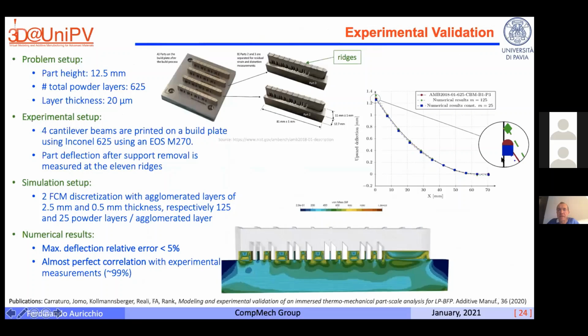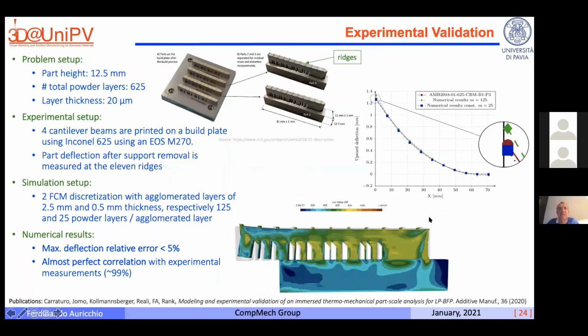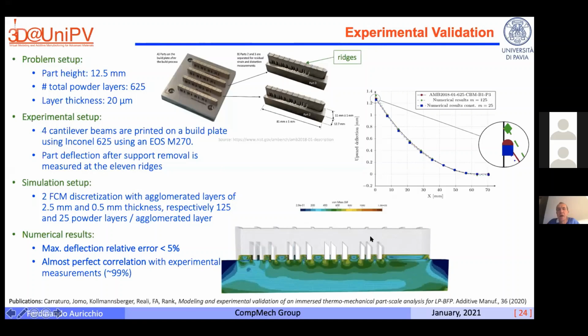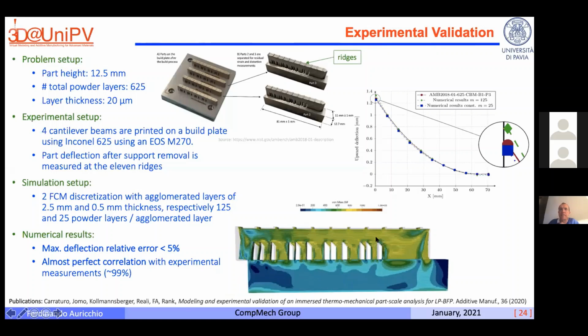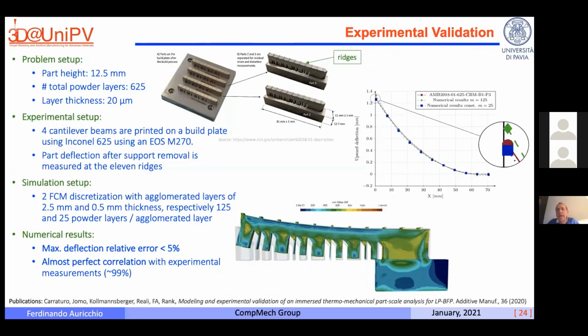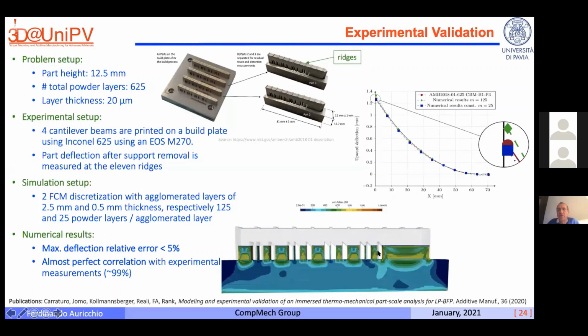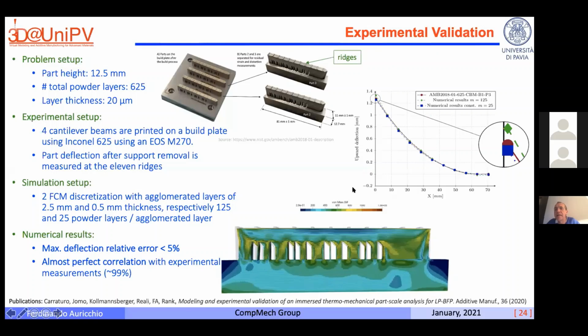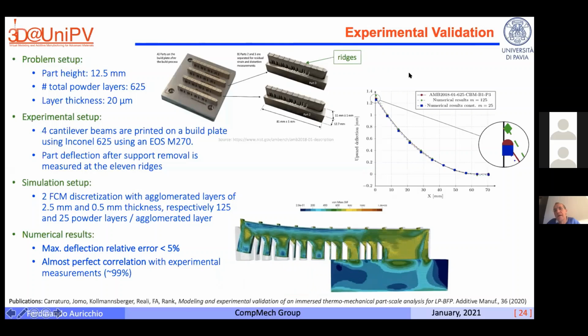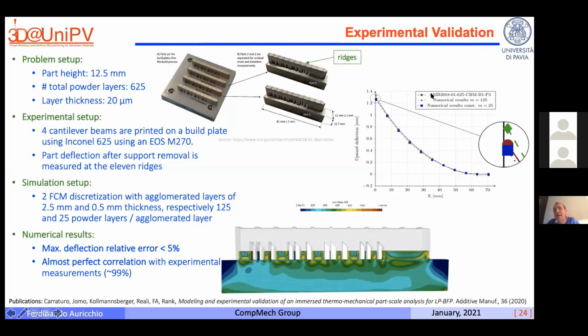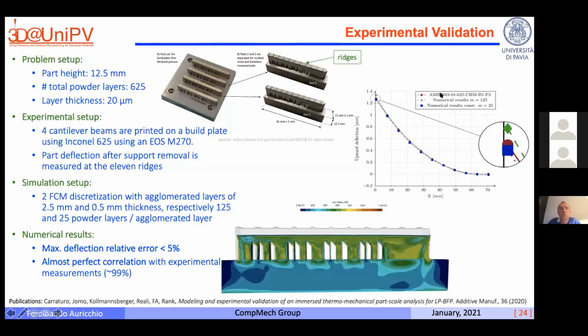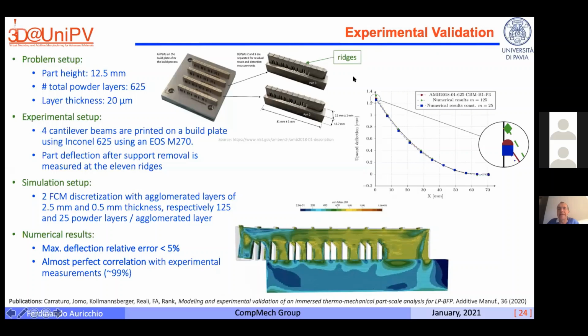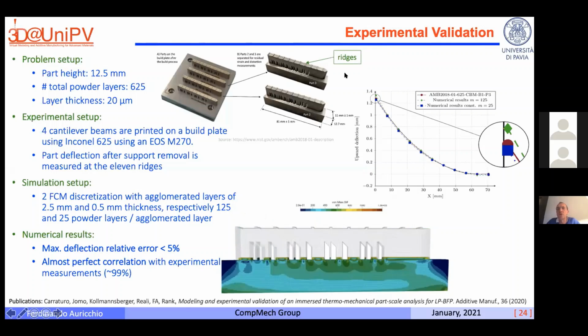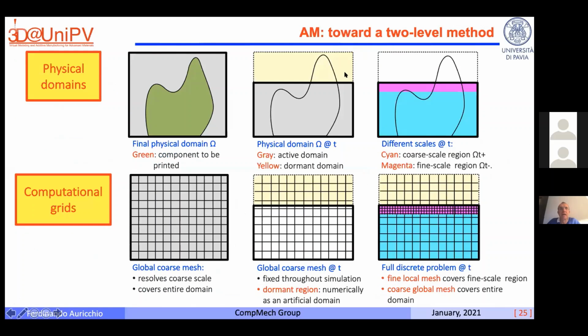And let me go directly to some simulation. This is a very classical simulation. It is the bridge, where we progressively simulate the deposition, the heating up, and the mechanical response, and also the cutting of the structure from the base plate. And here you can see some comparison between numerical results and experimental data, with a very good match between the experiment and the numerics. So I think the tool seems to be quite effective.